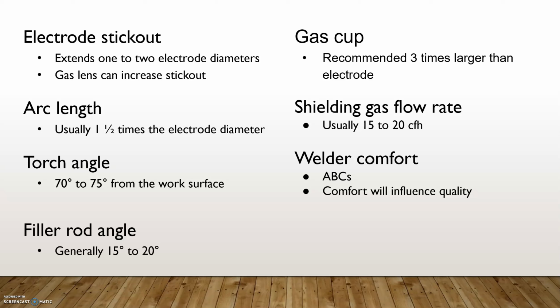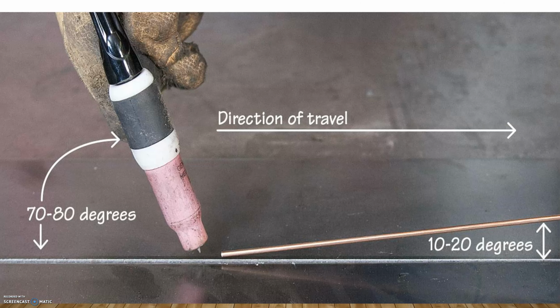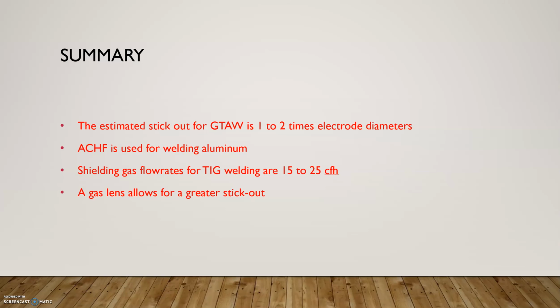Gas cup is recommended to be 3 times larger than the electrode. Shielding gas flow rates are usually 15 to 20 CFH. And welder comfort, always be comfortable. The more comfortable you are, the better your weld will look. There we have torch angle and filler rod angle. Quick little summary here. Stick out is on the test, so make sure you take these notes down as you're going along.